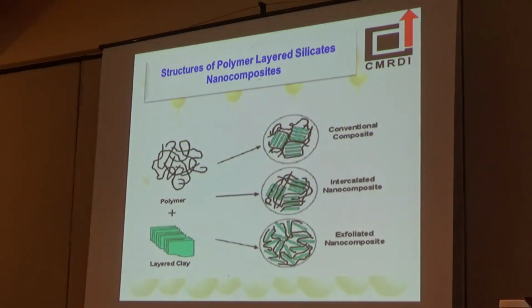There are three possible structures of the formed polymer layered silicate. The first structure is the conventional composite, in which layered silicates are dispersed within the polymer matrix, stuck to each other. The second possible structure is the intercalated nanocomposite, in which some amount of polymer chains diffuses between the clay layers, separating these layers to some extent, but still they are bonded to each other. The third structure, which is the most favorable structure and the one which has a great enhancement in the properties, is the exfoliated nanocomposite, in which layered silicates are dispersed within the polymer matrix, separated from each other.